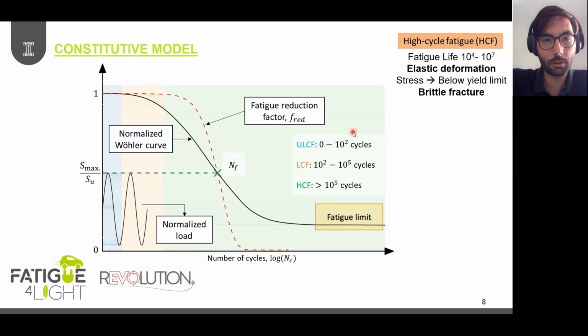And mainly, in order to use our numerical model to predict fatigue failure, we could be based on any discretization technique. We have chosen the finite element method, but it could be any other discretization. Basically, we need pretty standard material parameters like Young modulus for the stiffness, Poisson, and the yield limit of the material. This is for non-fatigue related behavior, but if we really want to simulate fatigue, we need a set of fatigue parameters. Well, in this case, our model is also based on standard information, based on the Wöhler curves, okay, that can be obtained experimentally.